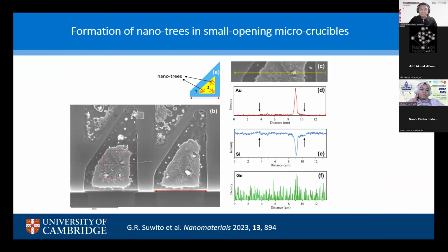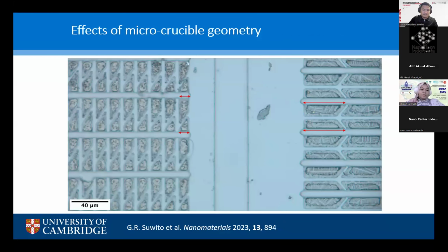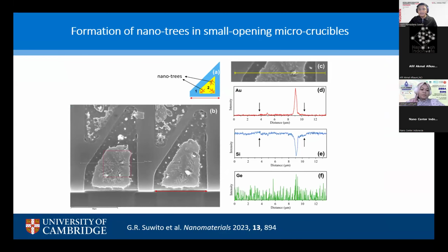Under an SEM, the first structure, on the left side of the previous slide, is shown over here now. You can see from SEM that these nanostructures look more dendritic, maybe like trees, so we call them nanotrees, with brighter regions in the middle. Here we have some leftover gold. However, the germanium signal is quite small, with very random noise. So possibly there is germanium, but very low. Further EDS investigations reveal that these nanostructures are actually quite rich in gold.